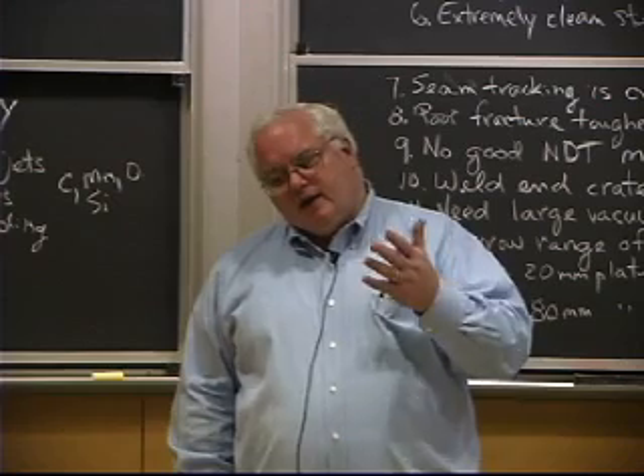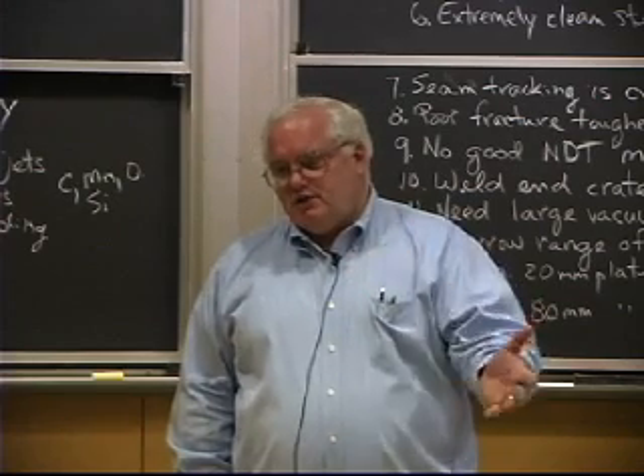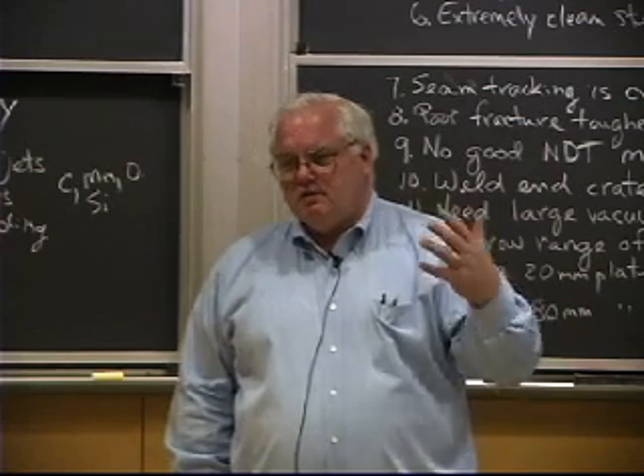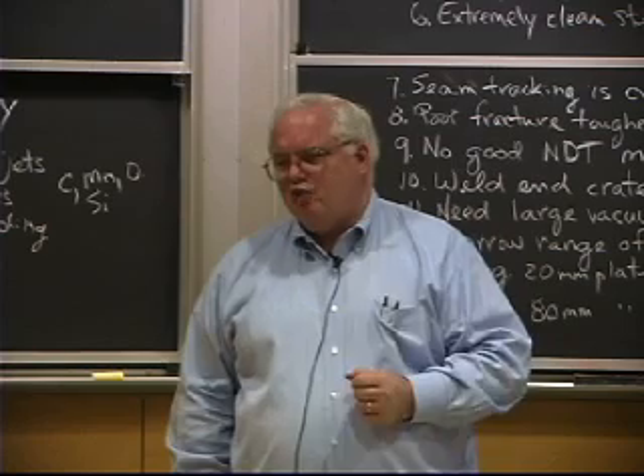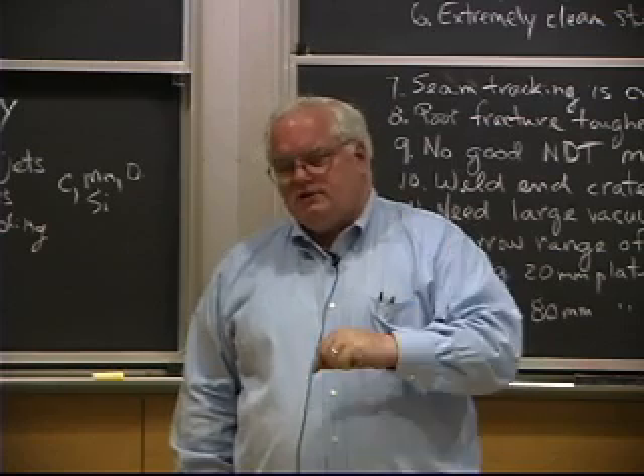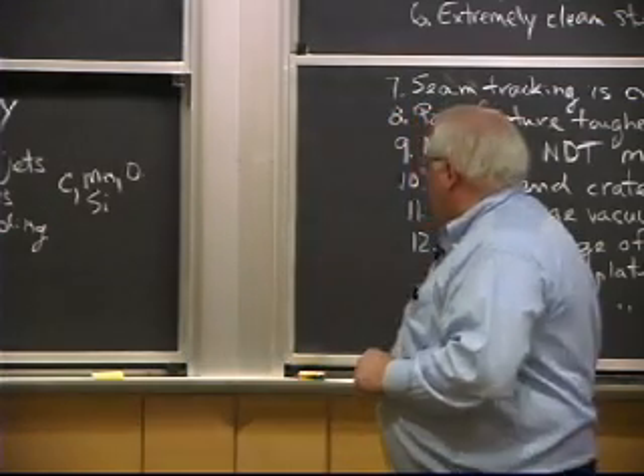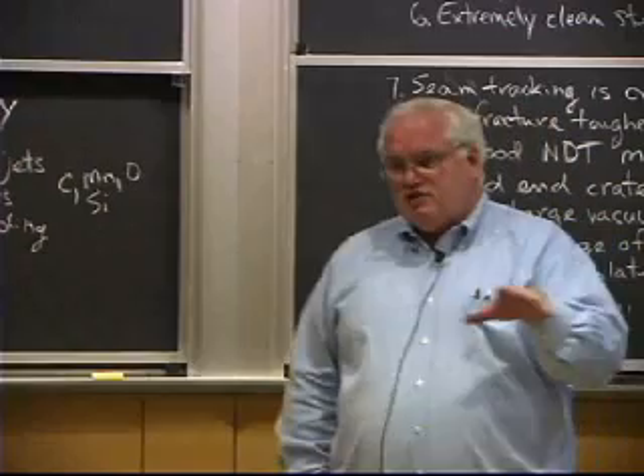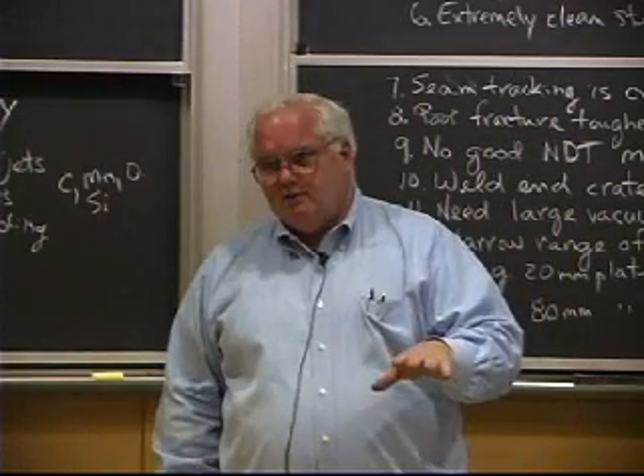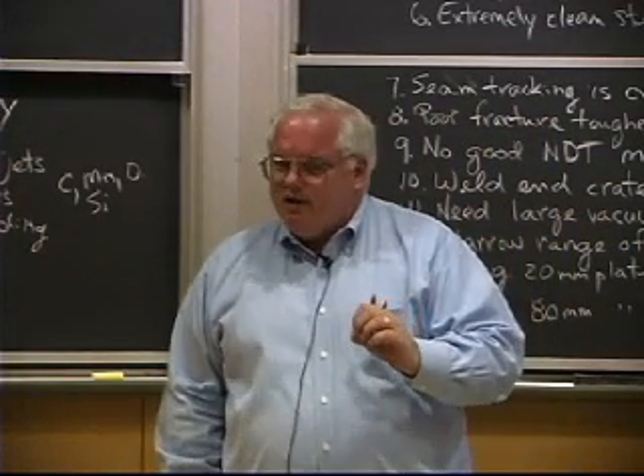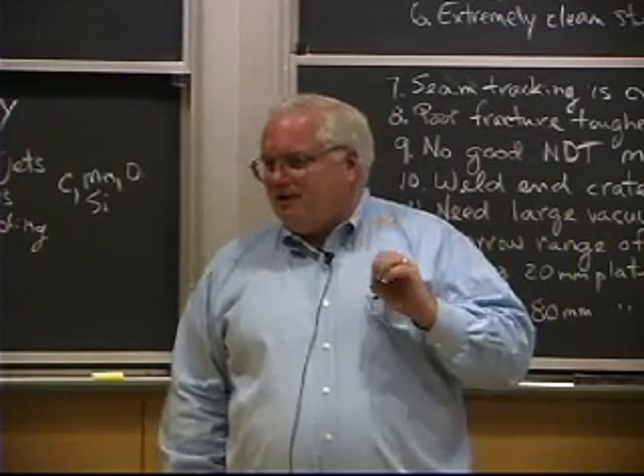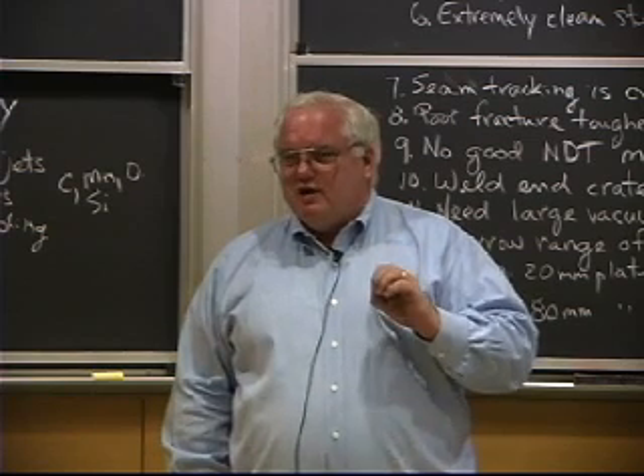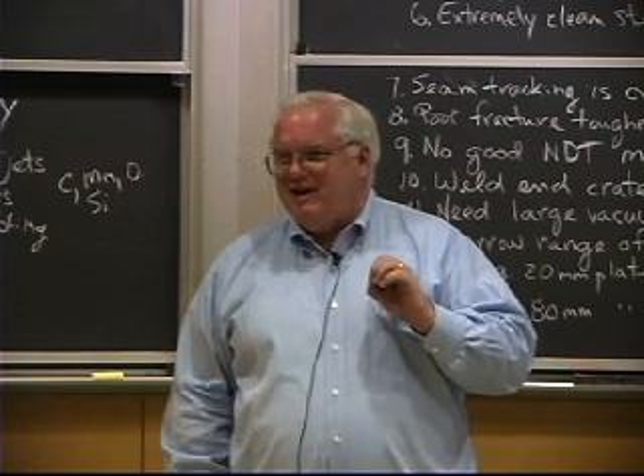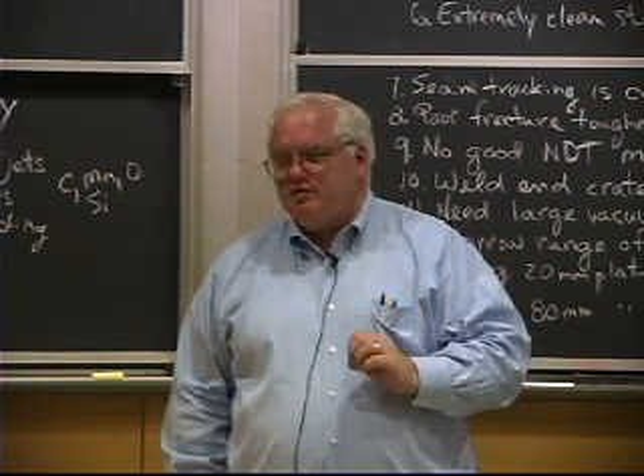okay? And if you're going to use 100% CO2, which is more oxidizing, you've got to use a richer chemistry wire. It turns out if you then use that with an argon shielding, and they'll sell you a different wire for argon shielding. Okay, now they also try to always sell you wires that'll do both, right? So they're not optimized for either. Okay, they're basically deficient in both respects.